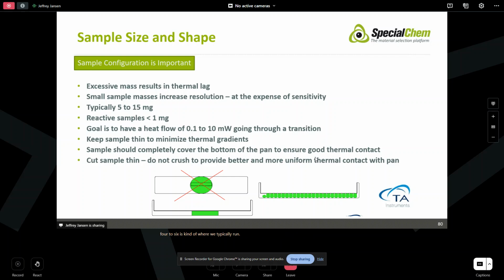Sample configuration is important. So you don't want to just throw this large piece in your pan and then crimp it. You're going to get small contact area. What you want is the maximum amount of contact area that you get. So what you necessarily wouldn't want to do is take an injection molding pellet, throw it into the DSC pans, and then crimp it. You're not going to get good contact between the material and the sample pan, which means you're not going to have good contact between the sample and the thermocouple, which is most important. So again, you want to try and make that.